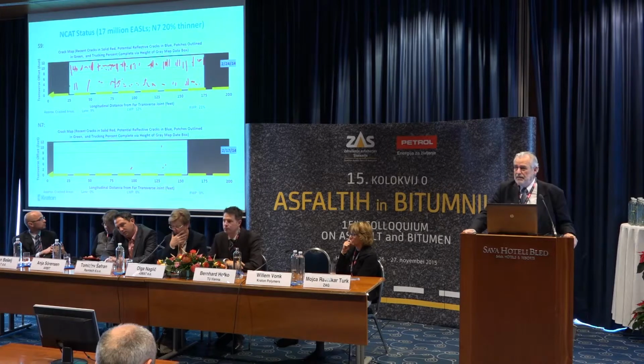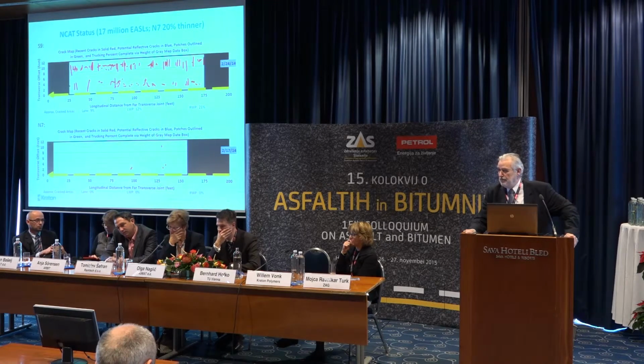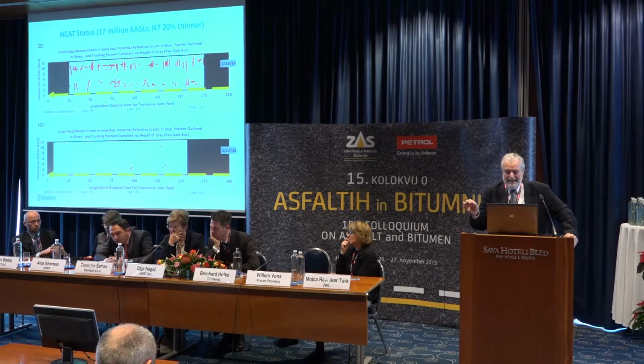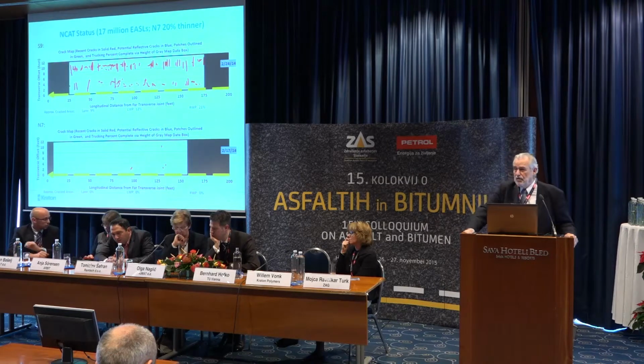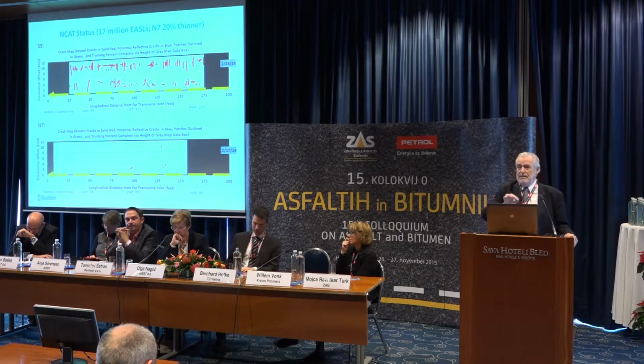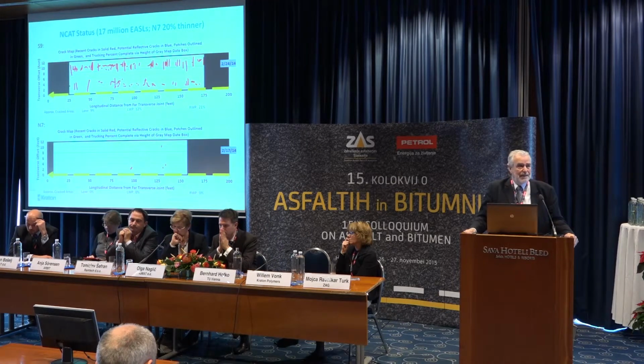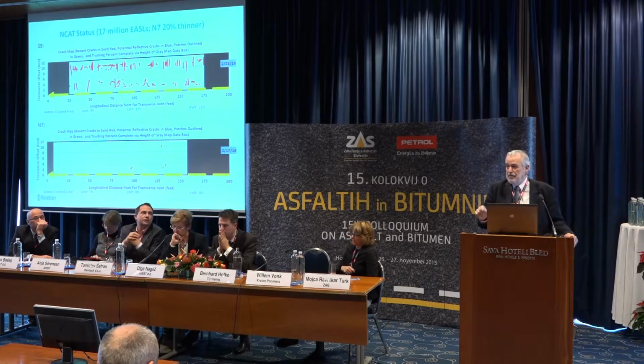After one cycle of testing, there was not much difference between the two sections. However, when we started to work in a second test period of 20 million ESALs in total, this was after 17 million standard axle loads. The damage in cracking of the surface of the reference side, which was 20% thinner, and on the bottom you have the cracking of the highly modified side. Why do I present here the 17 million standard axle loads? Because at that point in time they had to overlay the reference section, because otherwise there would be too much damage on the reference side.